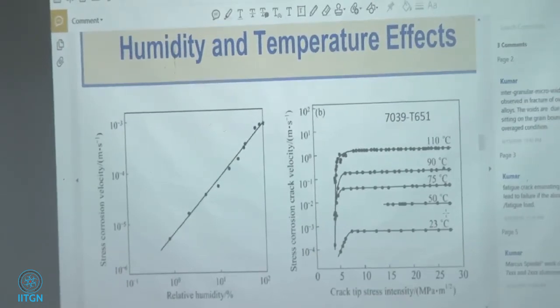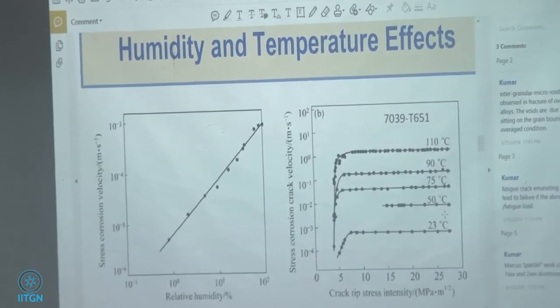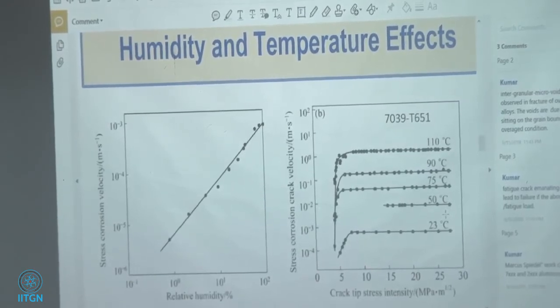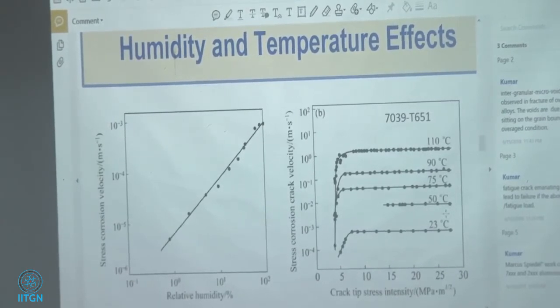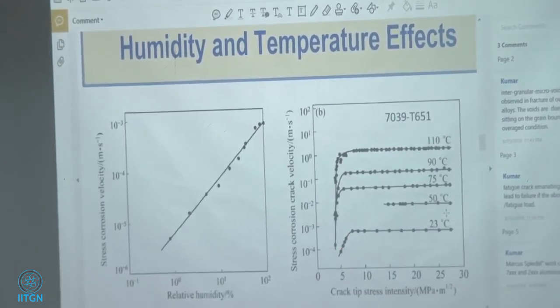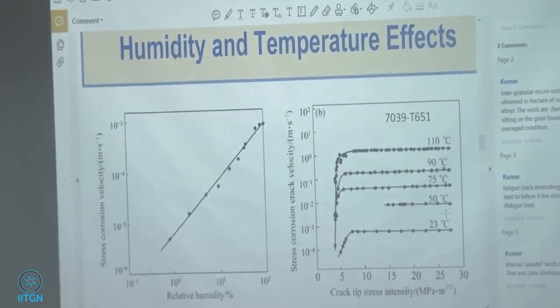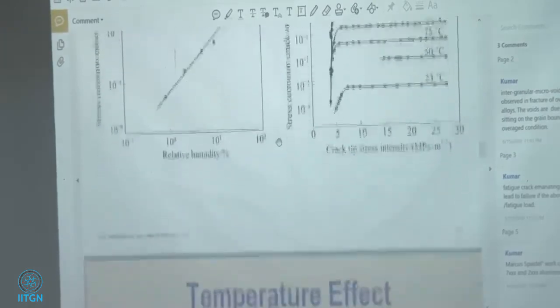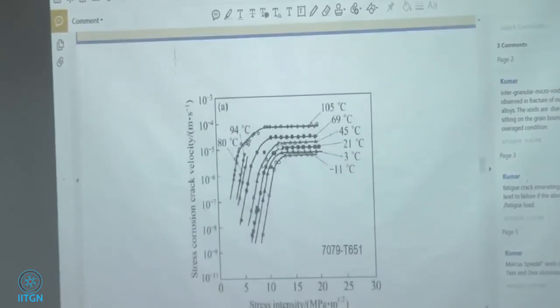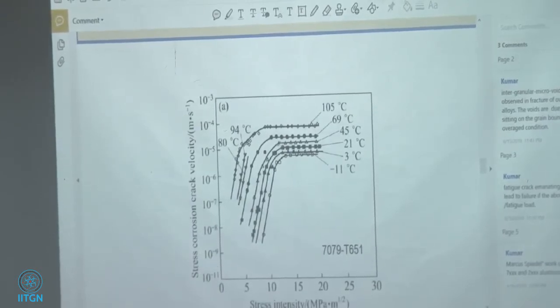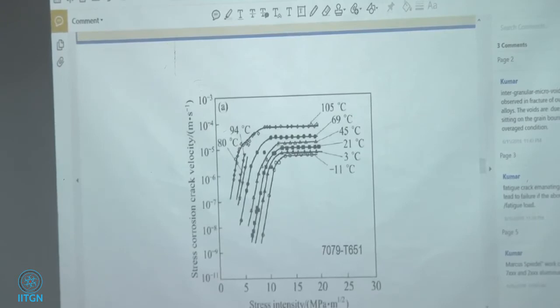So if you have a crack that has got a stress intensity K equal to sigma times square root of pi a, if you have a crack that's got a stress intensity of 5, you know what the variation would be, right? So people are still trying to model stress corrosion. There's a lot of work going on. Everybody's trying to do their best. How can we predict corrosion?